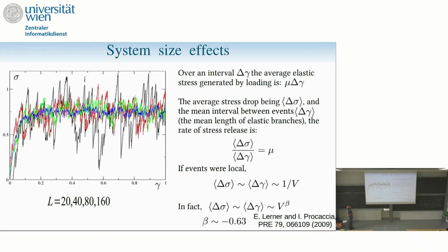So the first thing I do is, sorry, the picture is a bit ugly, it's old, but here you have stress versus strain for different system sizes. What you see is that the blue is the larger system size, the black is the smaller one. And so what you see is that, of course, that's expected, as the system size grows, the fluctuation decreases. And so you reach your elastoplastic curve. So you have this sawtooth pattern, and as the system size grows, these sawtooth patterns become finer and finer and finer, and that's how you reach plastic flow. But plastic flow, macroscopic plastic flow, is the endpoint of a sawtooth curve with elastic branches and plastic events.